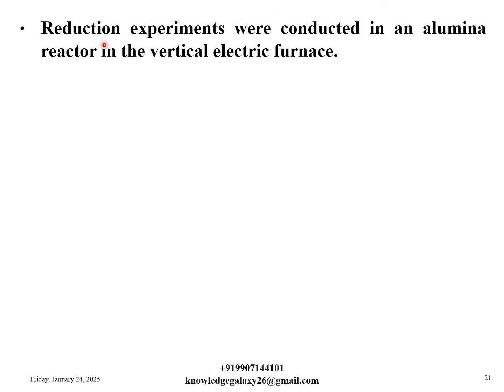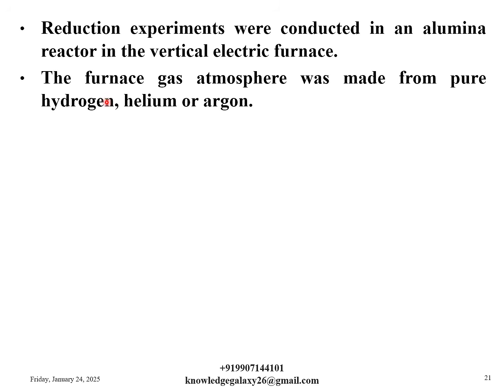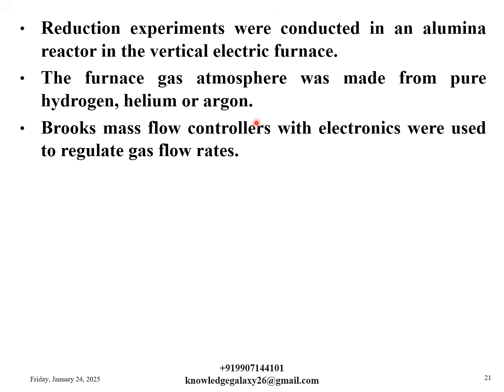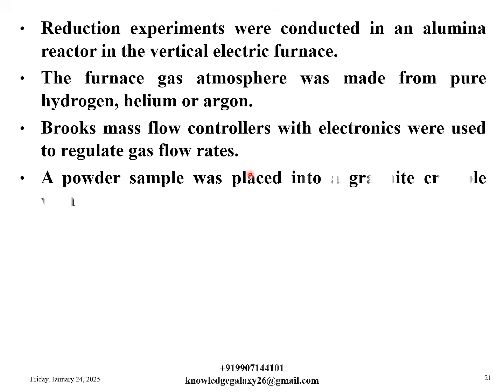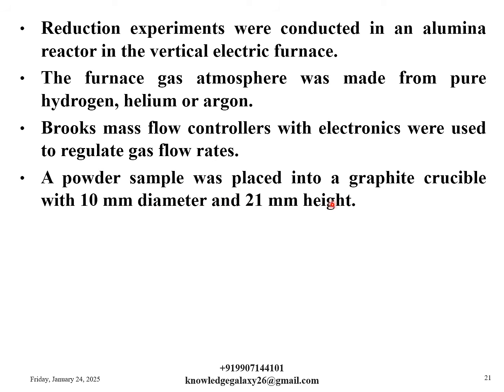Okay, now moving ahead. Reduction experiments were conducted in an alumina reactor in the vertical electric furnace. The furnace gas atmosphere was made from pure hydrogen, helium or argon. Brooks mass flow controllers with electronics were used to regulate gas flow rates. A powder sample was placed into a graphite crucible with 10 mm diameter and 21 mm height. The average sample mass was 1 gram.